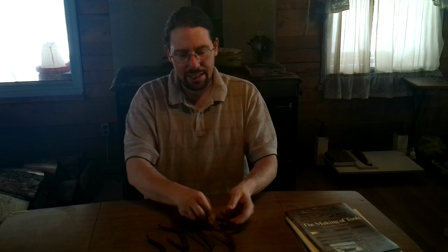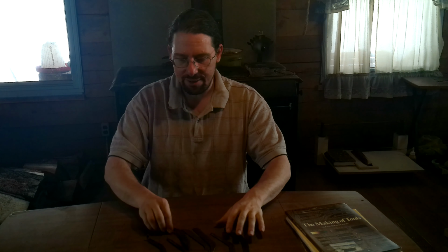So I'm not 100% sure, but an inclusion will have rounded edges, a crack will have sharp edges, and that's the difference. Now, if you don't file all the way through and get underneath that inclusion, it will eventually become a crack and break your blade. But if it's a little surface spall and it's got rounded edges, you can just file through it and you'll probably be fine, the majority of the time anyway. Okay? So you want to do those last things.